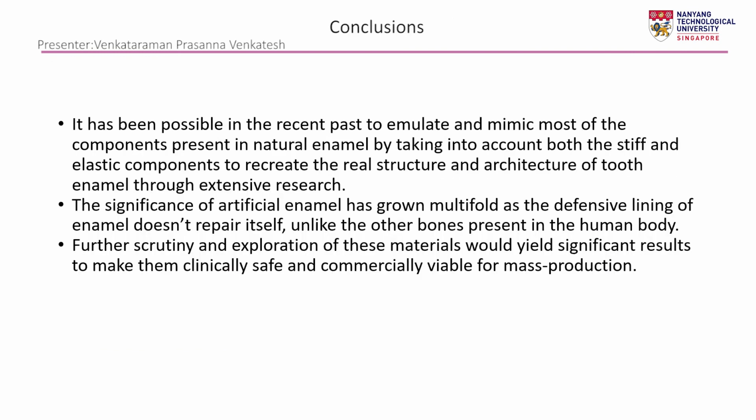In a nutshell, it could be concluded that a combination of parallel HA nanowires, amorphous intergranular phase, as well as organic nanofillers could be recommended to improve the mechanical properties of the artificial enamel as it combines contrasting characteristics like high toughness, strength, hardness, and viscoelasticity.